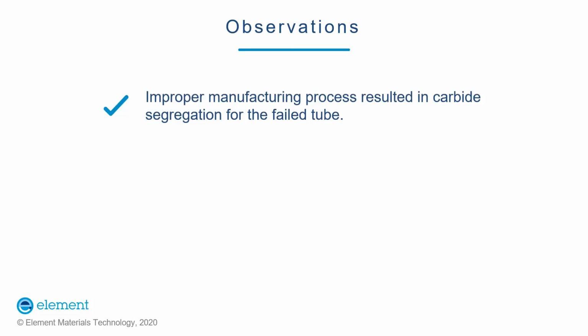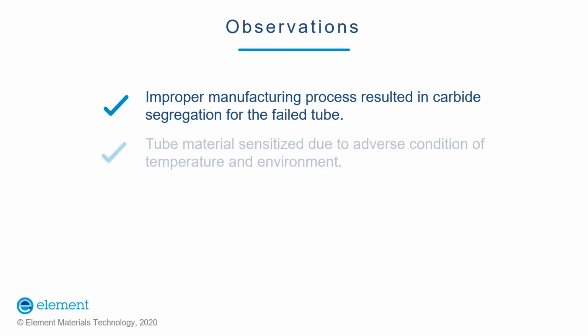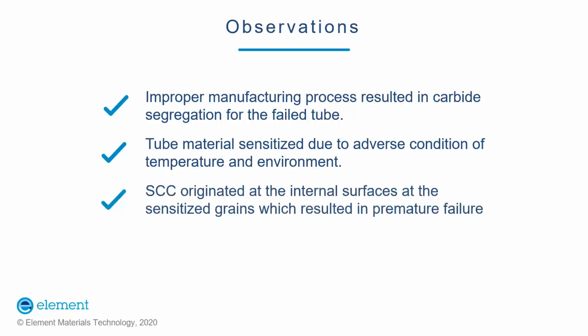Stress corrosion cracking originated on the internal surface and resulted in the premature failure of the tube, one tube. The stress generated during operation accelerated the process. Due to adverse environmental conditions, sensitization happened at a temperature even below 500 degrees centigrade. Sensitization followed by stress corrosion cracking, we can attribute to the unwanted microstructure of the failed tube, and that also explains why other tubes didn't fail and only one tube failed.